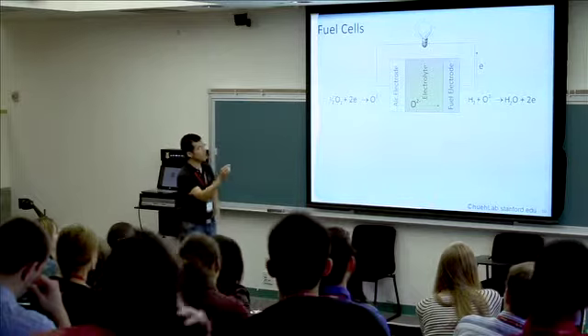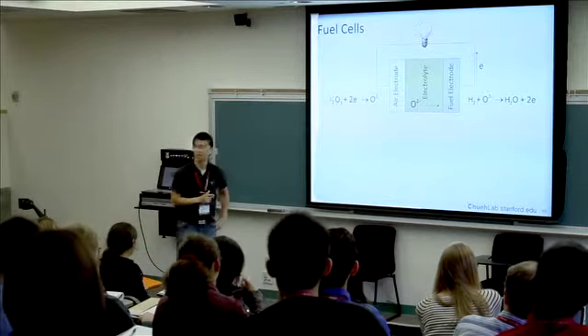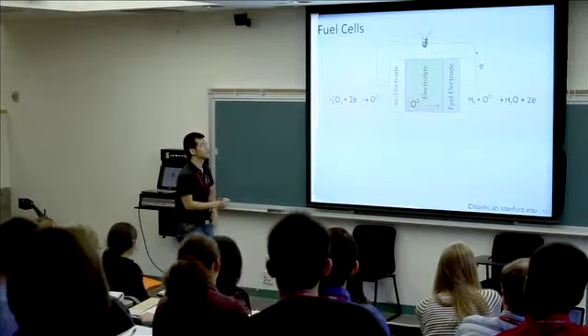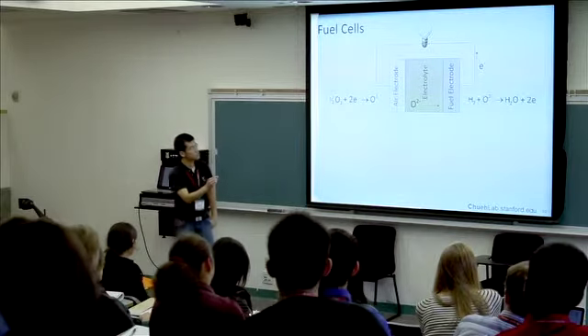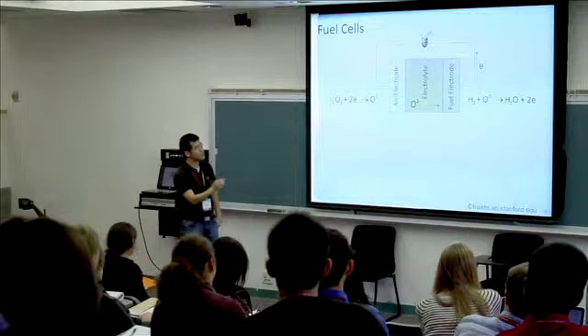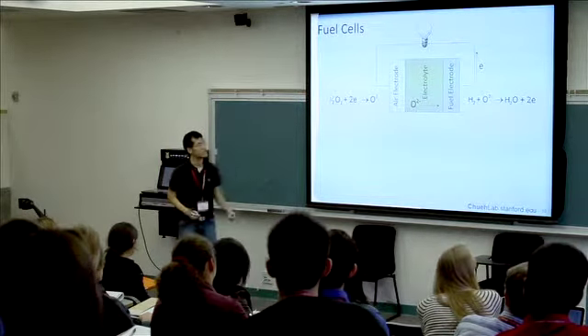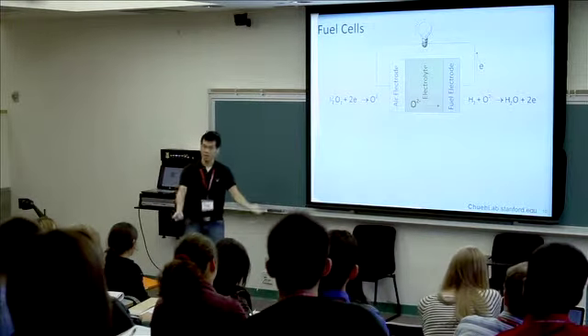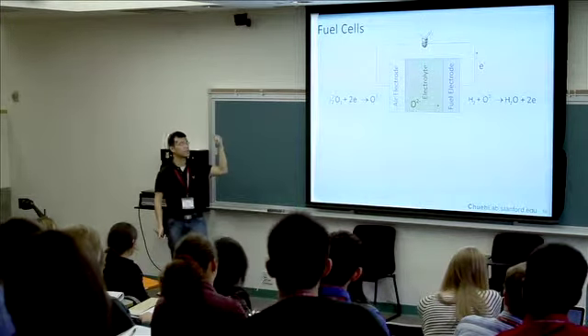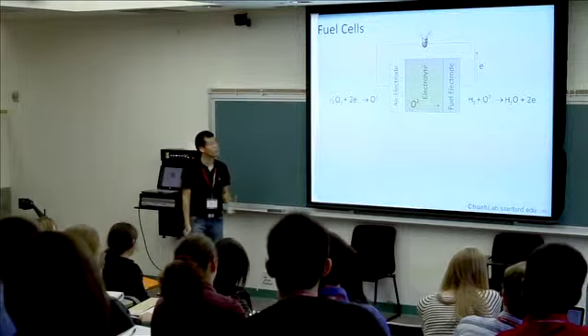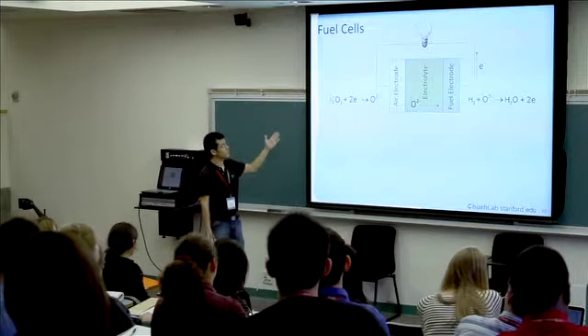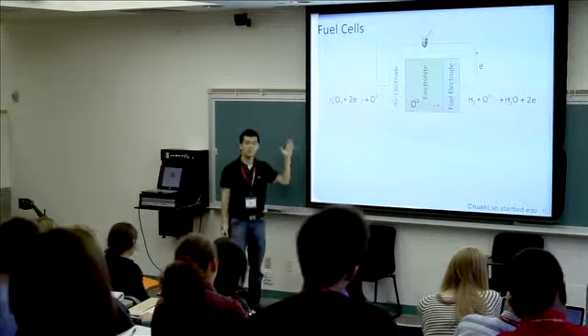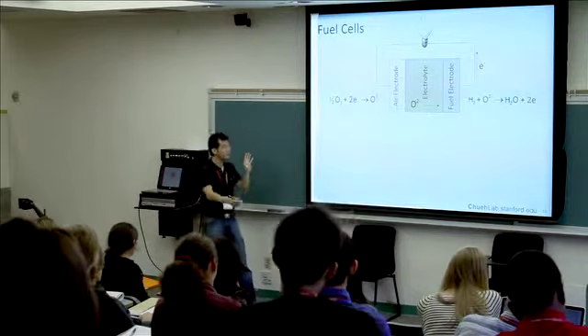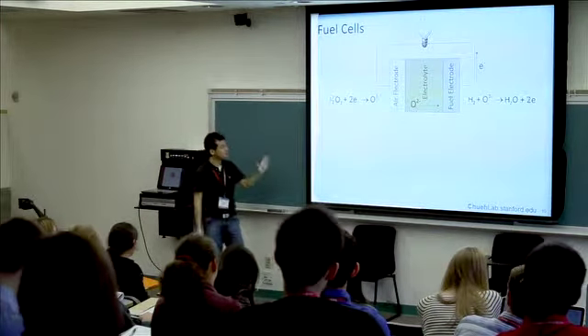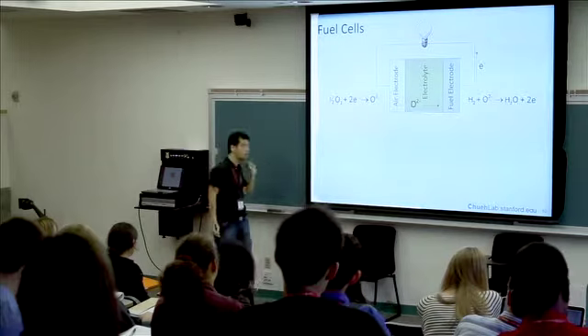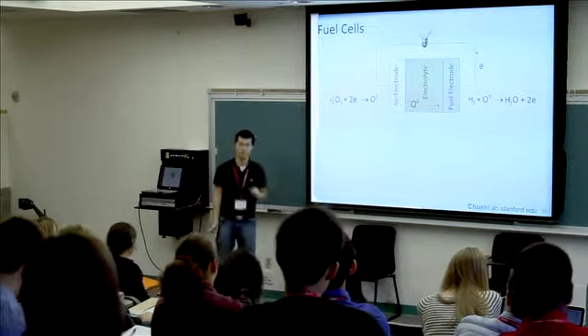So on the fuel side, we have a fuel electrode. In the fuel cell, this is called the anode because of the direction the electron transfers. So we have hydrogen reacting with oxygen ion that's coming through from the other side, producing water and then an electron. And this electron goes to the outside circuit, powering some sort of a device. On the air side, we have the complementary reaction, which is the incorporation of air. So you take air, you bring that electron back, you combine it, you form an oxygen ion, and you push the oxygen ion through the electrolyte.